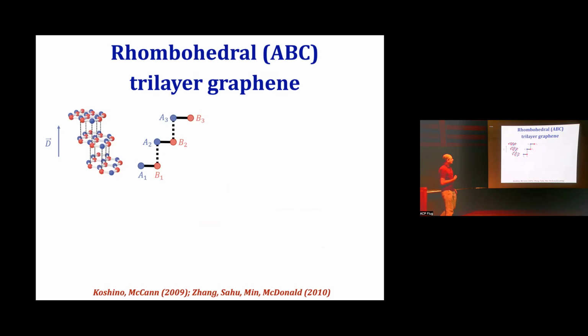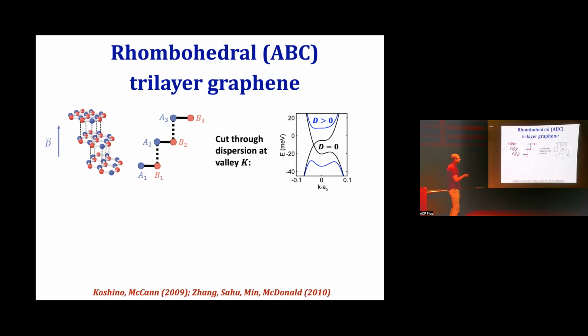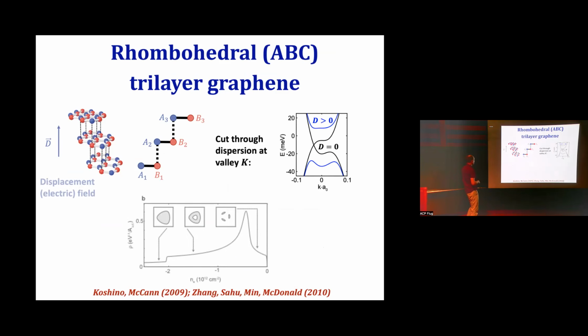So this is again rhombohedral trilayer graphene, 3 layers of graphene stacked in this ABC way. And it turns out that a very useful knob to make the energy bands even flatter in the system is a perpendicular displacement field. You can apply basically an electric field perpendicular to the system. You start from these very narrow dispersions close to low energy. You see here that it's not quite k cubed. This is from smaller terms in the Hamiltonian that I didn't discuss.